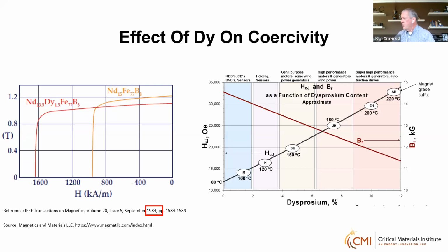And the graph on the right shows the impact of various levels of dysprosium on the maximum application temperature. At one extreme, if we have very low levels of dysprosium or even zero dysprosium, those magnets can't really operate above 80 to 100 degrees C. Whereas at between 10 and 12 weight percent dysprosium, we have magnets that can operate in applications above 200 degrees C. So that really became the solution to the poor thermal behavior of the ternary system.